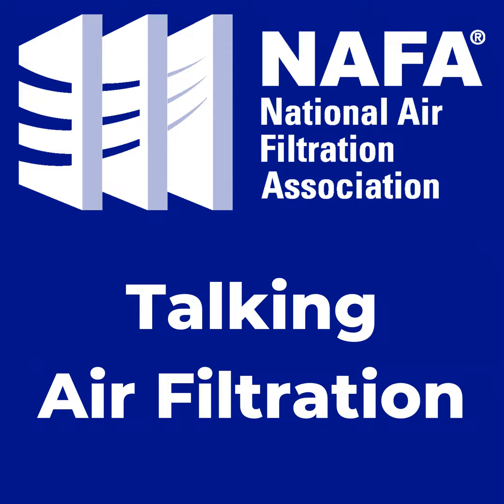And really, why do we use nanofibers? There are some really unique properties to nanofibers that come from these nano-dimension structures. So you have a high surface area to volume ratio. Basically, you don't need a lot of weight of nanofibers to have the effects on the property of the whole fiber mat. So you're not really measuring it like GSM or something like that with other processes. You can have a thin coating that's barely, negligible in terms of weight to the whole fiber structure, but it'll be putting the properties on.